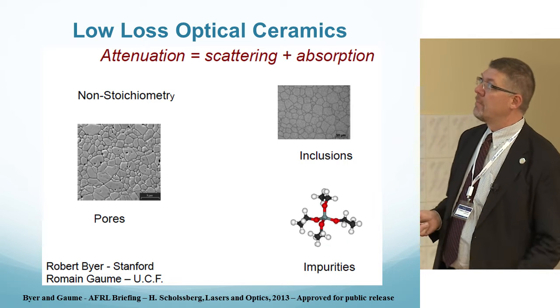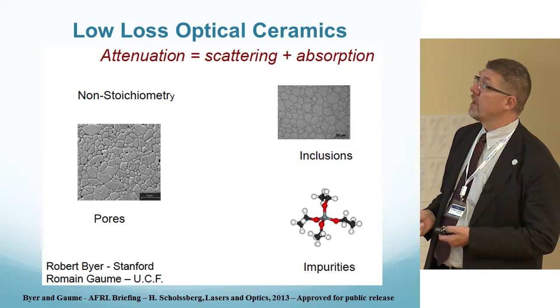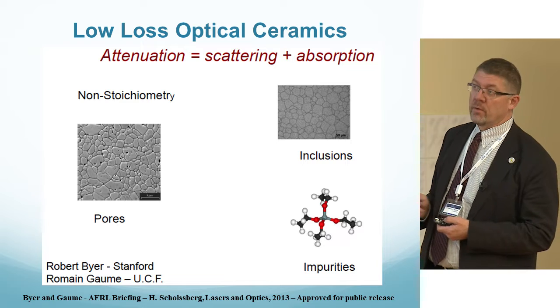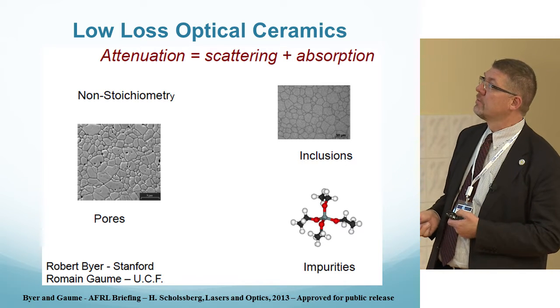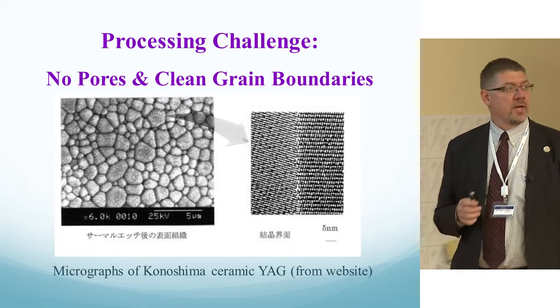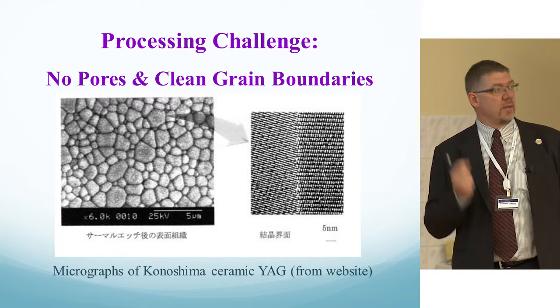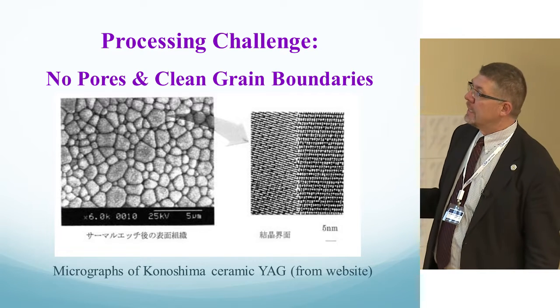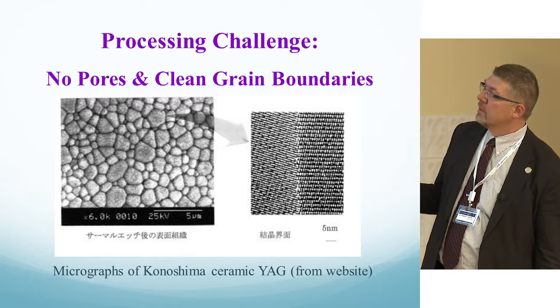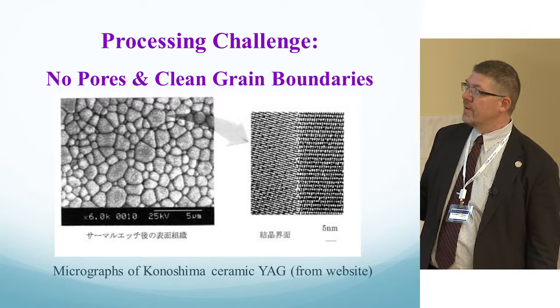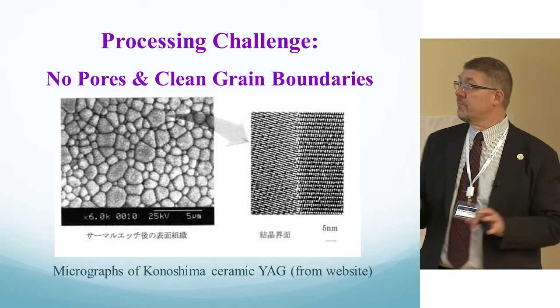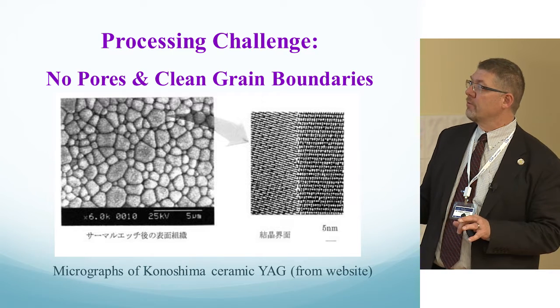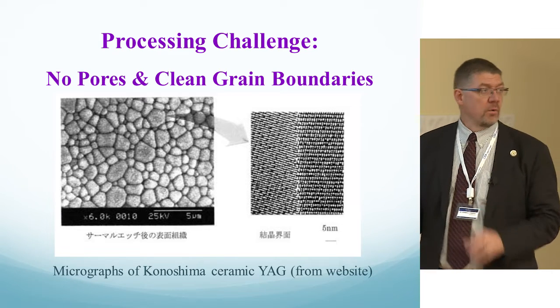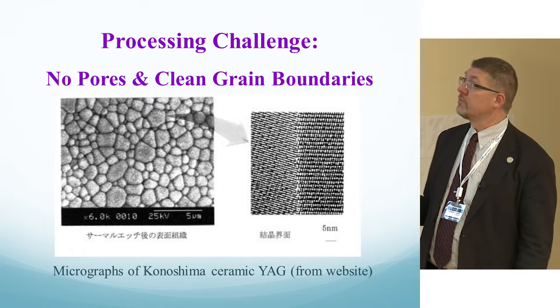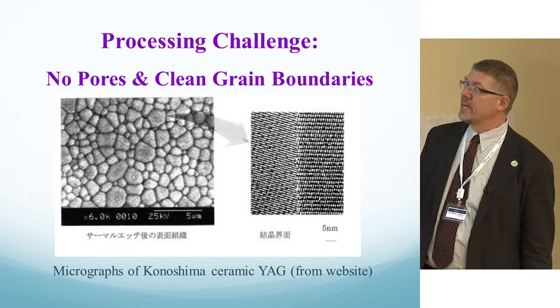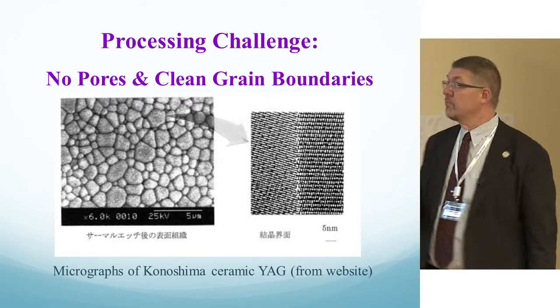Romain Gaume and Robert Byer have been working on this for a number of years at Stanford. George Boulon up at Lyon has also been working on this. But the real processing challenge is getting rid of the pores, keeping the grain boundaries clean. Two of the photographs from Konoshima show this, which shows very nice grains, slightly different sizes. Your bar down here is about 5 microns, so these are on the order of micron-sized grains across. But they're lined up very nicely, and they're clean interfaces.